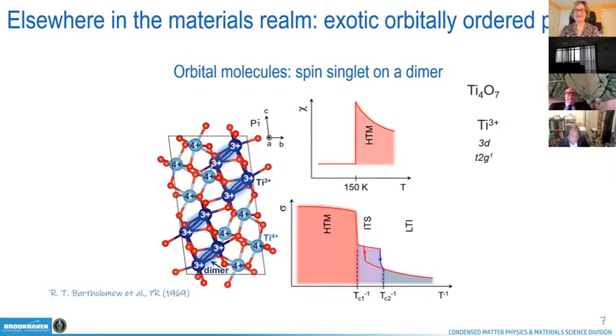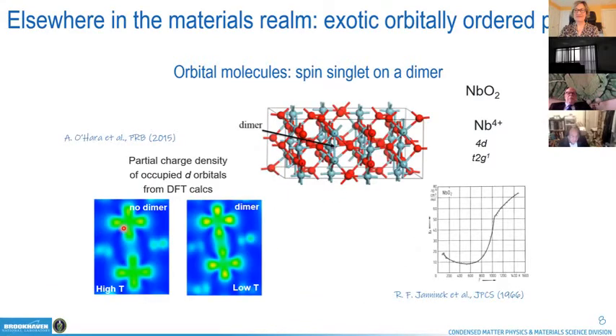Interestingly enough, all that work was done initially like 60+ years ago, just like manganites. Or niobium dioxide. Again, we have a sharp drop in susceptibility. Here is a more recent work where we see a cartoon of partial charge density of occupied d orbitals as it comes from DFT calculations. So at low temperature, you have dimerization that presumably looks like so. And at high temperature, you have no dimers, and this is its depiction.